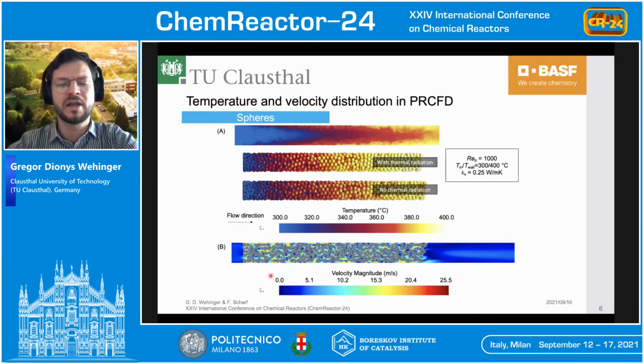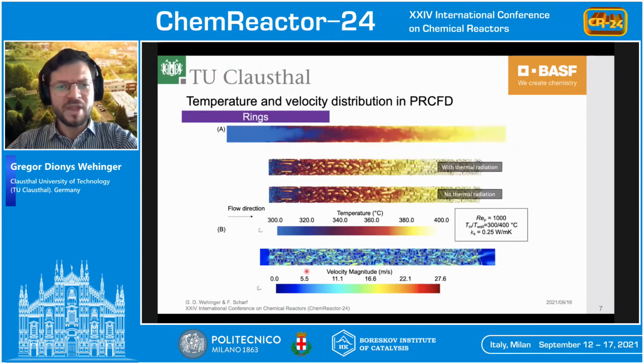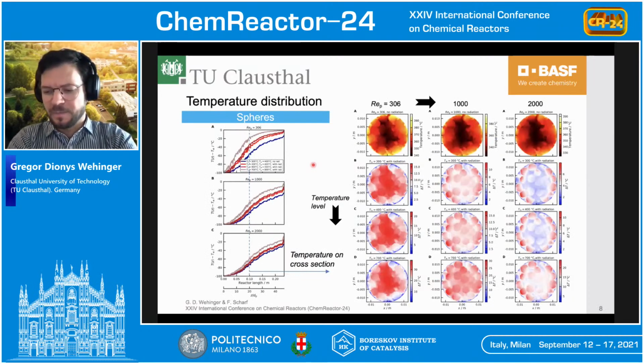And on the bottom, you see a typical velocity magnitude distribution. So we see acceleration zones in the near wall region. So this is this wall channeling that you might know. And then where particles are pretty close together, we sometimes see velocities pretty much approaching 0. So we have stagnation regions here. So really complex. And it's even more complex for the packed bed of rings, as you might see here. But once again, this thermal radiation plays a significant role as an additional heat transfer mechanism, especially where the temperature gradients are pretty high. So let's move on to the quantitative results.